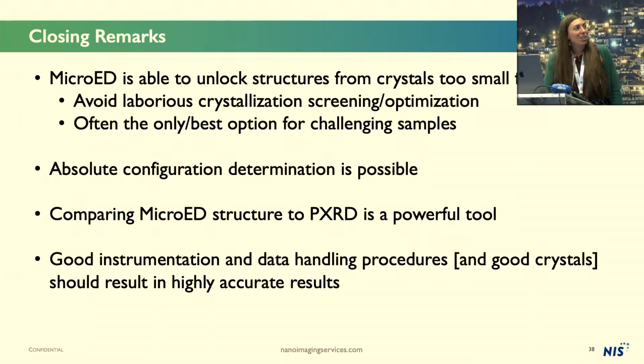All right, I will just toss out some closing remarks and just say that with micro-ED, we're able to unlock structures from crystals orders of magnitude too small for single crystal X-ray diffraction. This can avoid laborious crystallization, screening, and optimization. And in many cases, this is the only or the best option for challenging samples. Absolute configuration is definitely possible from these data.